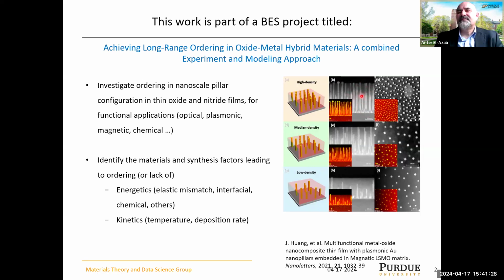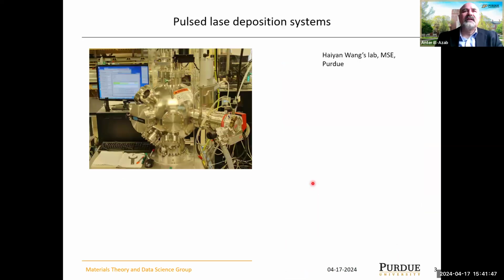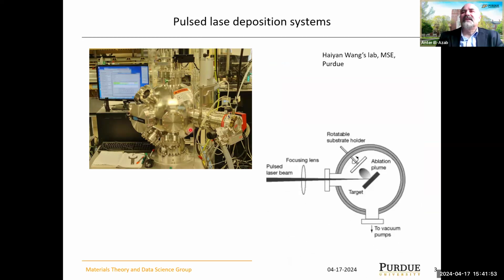We use a variety of combinations of materials to grow these things using pulsed laser deposition. Our goal is to understand the energetics of these systems and the kinetics of growth as well. The growth itself is done by this fancy pulsed laser deposition device. I like to simplify it to this picture here. It's a chamber under vacuum, and laser pulses come to a target material that evaporates the material and deposits it on this substrate. So the useful material that we collect comes on this substrate at the end.